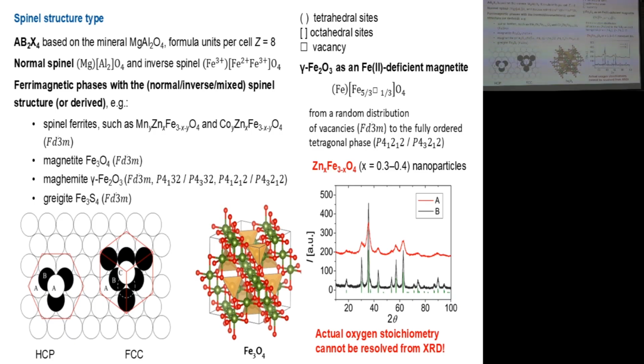And there are many important compounds that belong to this structural type, especially various spinel ferrites, manganese zinc ferrites, cobalt zinc ferrites. The well-known magnetite is actually the inverse spinel, with this kind of situation that the divalent cation is going to the octahedral sites. But also, for example, thiospinel, greigite. And importantly, the well-known maghemite is also derived from this crystal structure, and you can describe maghemite as like iron 2+ deficient magnetite.